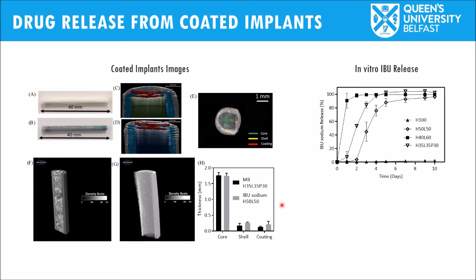Not everything was good news. For example, with ibuprofen sodium, again due to the high solubility of these compounds, we couldn't get sustained release profiles, because the water that can permeate inside the implant was enough to dissolve the majority of the ibuprofen, and the release was quite fast. So these membranes are promising, but they need to be evaluated for specific examples. For each drug that can be loaded in implants, the release rates need to be checked carefully, because the solubility of the drug will influence the release rates massively.